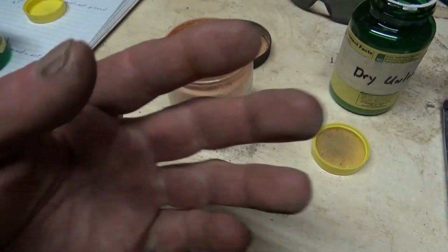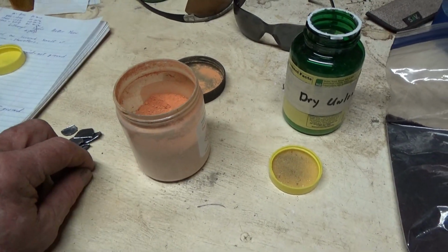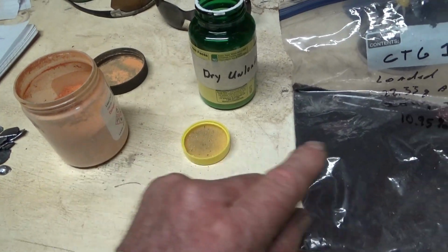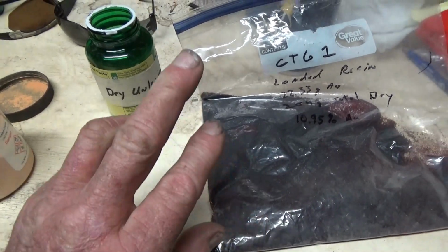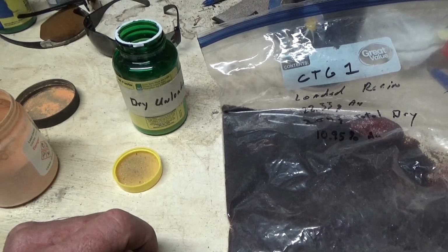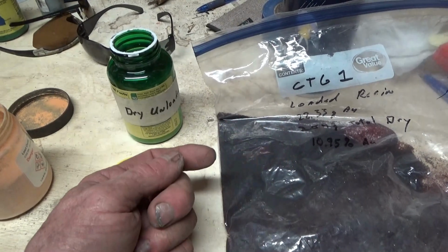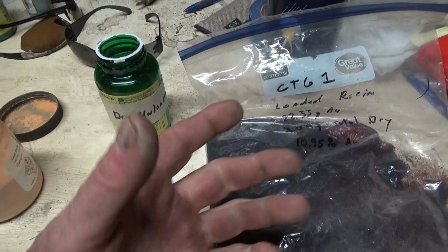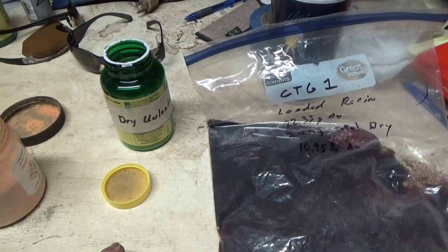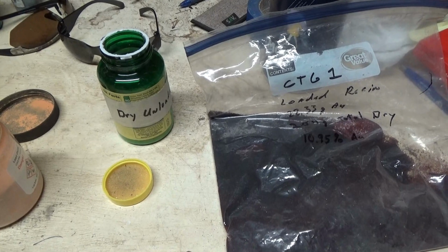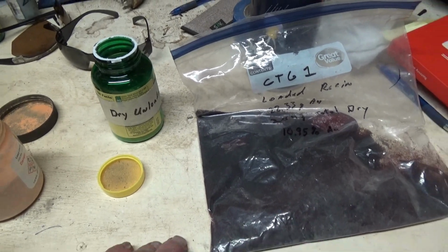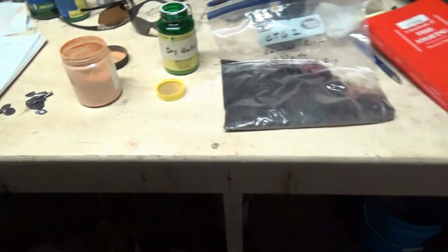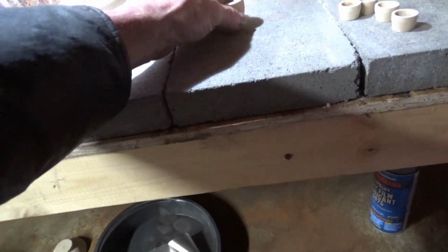Now, when that's all blended together, the theory is, and what the hope is, the resin that has the gold in it, as it's exchanging the carbon and hydrogen for the oxygen with the lead, the gold will get stuck to the lead. The lead forms droplets, goes to the bottom of the crucible, and then at the end of the melt you pour it into that cone mold warming up there. You get a lead button, and then you cupel it. Again, we're essentially fire assaying this stuff.